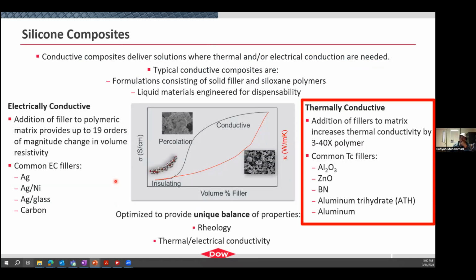So these are composite materials. So the reason why you would want to use an electrically conductive material or a thermally conductive material is usually in electronics when you want to avoid potentially short circuiting an electronic or having electronic overheat on you. So in all electronic spaces, and today we'll talk only about thermally conductive materials, but in all electronics, there is a heat source. So as the instrument is on, for example, it's heating up. There's a heat source and a heat sink. And you want to pull heat away from the heat source into the heat sink. And so we have these materials that sit at the interface to help that happen.